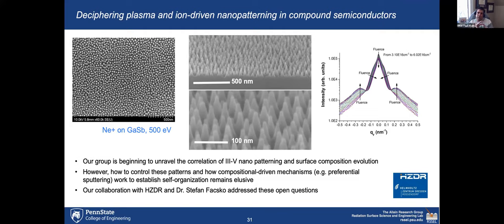Because it's also dependent on that, there is a time scale in which you spontaneously generate these patterns. But it turns out, going with the earlier question, that if you modify the subsurface phase separation in such a way, you can reach, for example, a metastable phase. And that metastable phase will remain stable. That is, these structures that you see here, you can keep those structures. They will remain this size and this shape for a very long time. So they're stable once your radiation is complete and all the thermal processes are complete. These structures remain very stable over very long periods of time. We have not tried negative ions, to go back also to your question, in these studies.